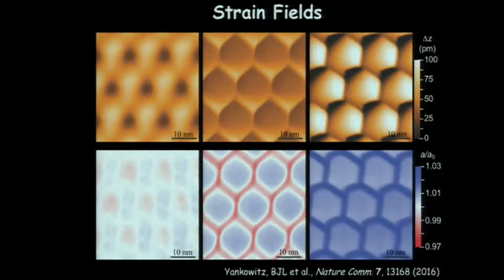Okay. So these are the results for the 3 imaging conditions. This was the one that I was just showing, roughly the same one. If we don't push very strongly, there's actually a very weak effect here. There is still some effect. You can still see a slight variation, but it's on the order of 0.2, 0.3% or something. If you start pushing stronger here, that's when we can get basically this full 2% lattice strain.